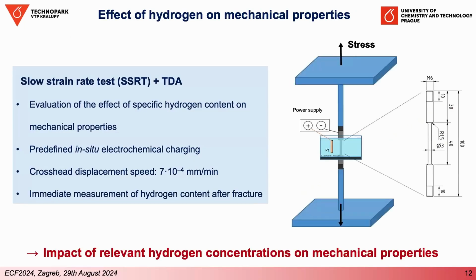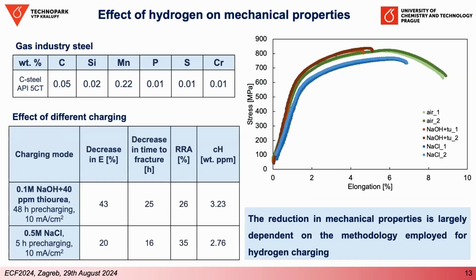And then we are running some mechanical testing where we are trying to play with parameters to really receive more relevant data, because we started with the basic solution with the addition of the recombination poison, and we saw a drastic effect of the hydrogen mainly on elongation, but we know that this is not a realistic scenario. So now we are using a milder approach, and we are still able to see some effect. But we know that it's a really big simplification compared to gaseous charging.